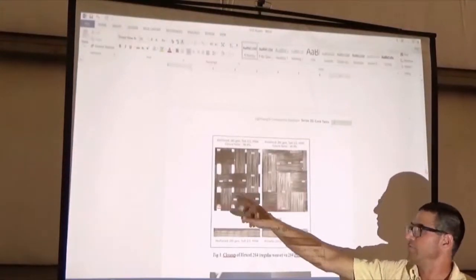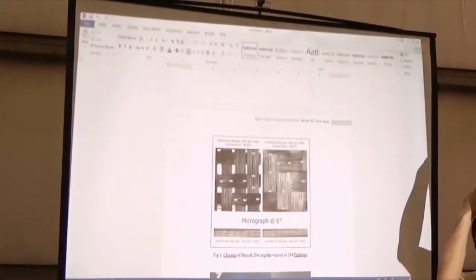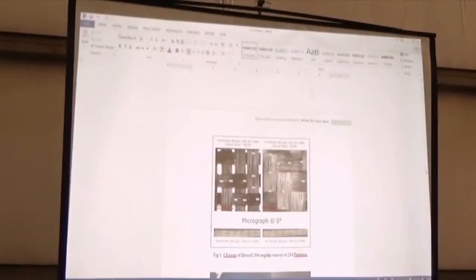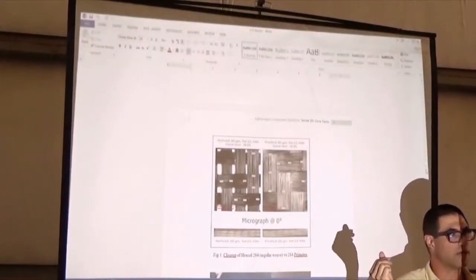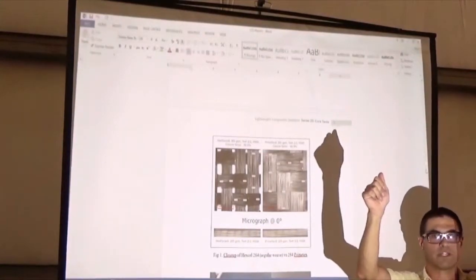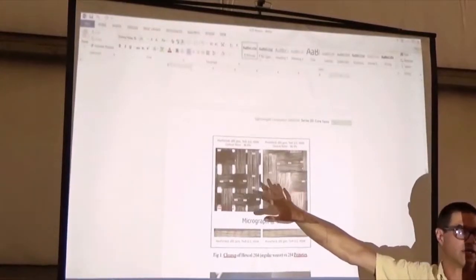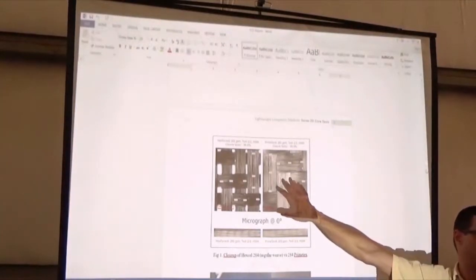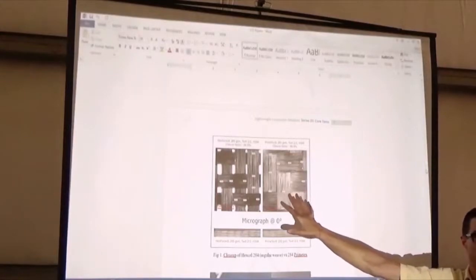So you can see that regular 282, if you hold it up to the sunlight, you'll see a lot of light coming through, because you have a lot of interstices here where the weave is not very tight. So one of Hexcel's new products is something called PrimeTex. It's the same weave, it's the same tow, but they spread the tow a little bit out when they weave it, and so when you hold this up to the light, you see hardly anything coming through. So they're banking on the lower amount of crimp to increase the strength. I like this stuff because it handles really nicely, and I have wet wings, and so I wanted to have a really tight weave carbon fiber so that I wouldn't have to worry about leaking in the wing.